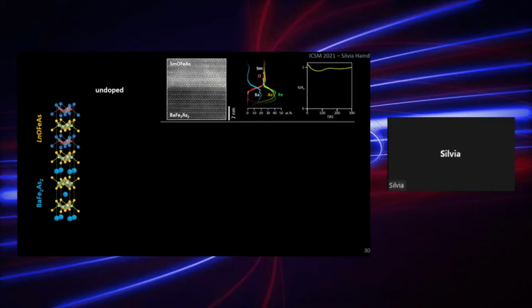So you see here 3 panels: a TEM image, an Auger electron spectroscopy depth profile, and the result of a resistivity measurement on that bilayer structure. And you can see here that we find indeed the interface at the commonly shared iron plane. You see also in the Auger electron spectroscopy that the interface is very sharp. We can really distinguish the iron oxypnictide from the 122 layer. And because this film is undoped, we do not expect any superconductivity here. And this is what we actually measure.